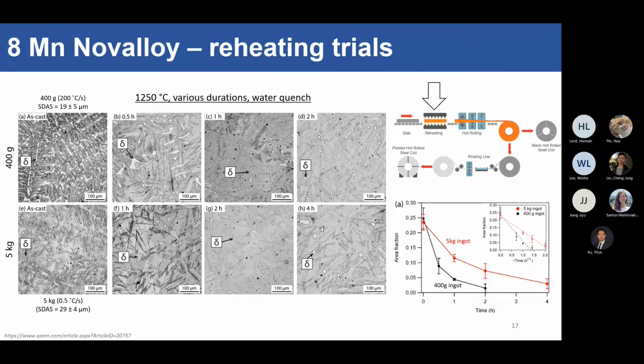Great, so we cut it up into small chunks, and then we homogenize it at 1250 degrees, which is what you see in a continuous reheating furnace, and for different times. And you can see here in the as-cast structure these little white dendrite skeletons, and that's actually your delta ferrite. Remember, steel solidifies as delta ferrite first and then transforms into all the other bits. But for this case, you have delta ferrite that has been stabilized all the way back down to room temperature, and that's a bad thing.